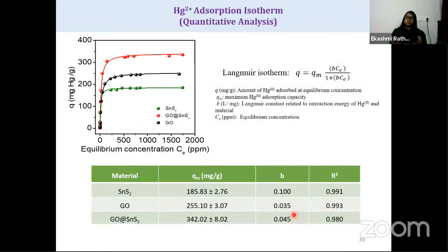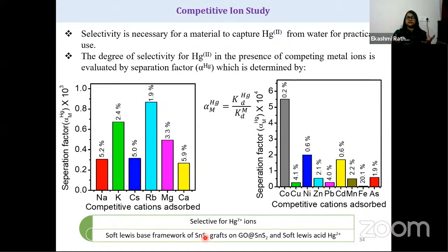Now we wanted to know how mixing these two is helping the capacity to increase. If you can see, graphene oxide and SnS2, the red compound, is outperforming the other two, only graphene oxide and only SnS2, and there is an increase in the capacity of the material. So that's how we introduce selectivity in a material and how we design new materials. We did a competitive ion study with other metal ions like sodium, potassium, cesium, all those monovalent or divalent ions, and we found that it's highly selective in nature.